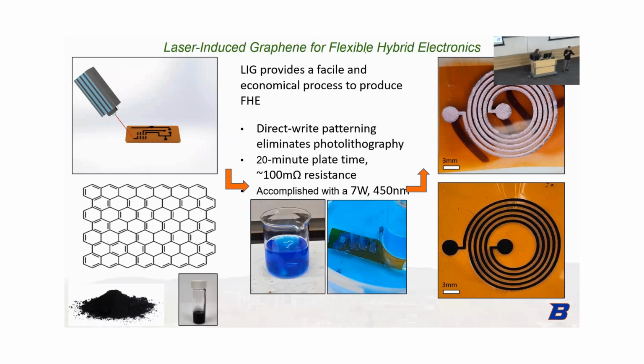The answer is yes. And I accomplished that by putting palladium into my laser-induced graphene. Palladium is an extremely active catalyst. So if you put it in solution, it will selectively reduce copper ions, and you can plate copper on top of the laser-induced graphene, and you can make a flexible circuit doing this. That's interesting in and of itself, but what's the greater justification for this?